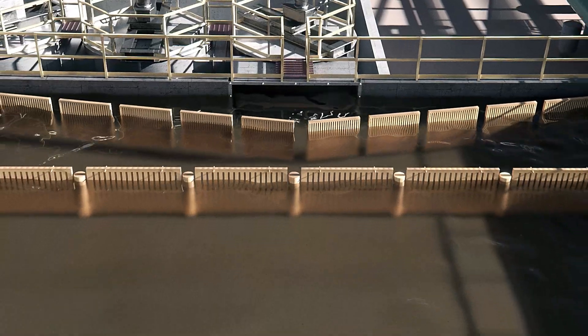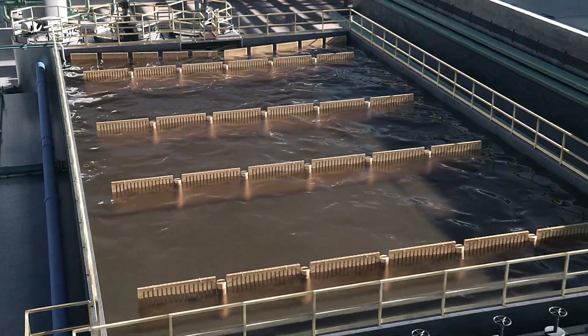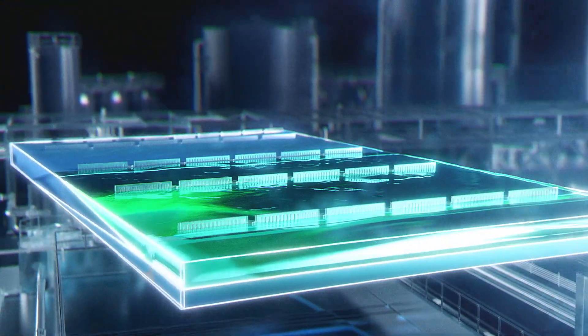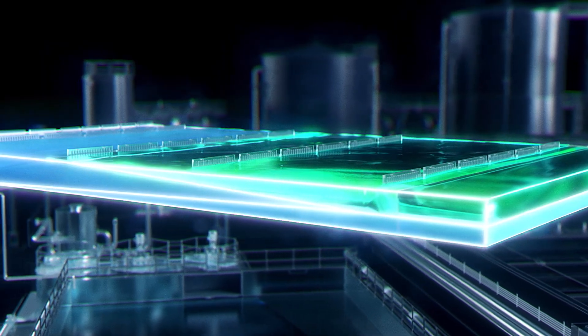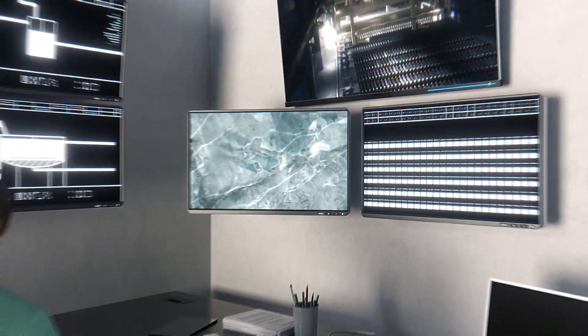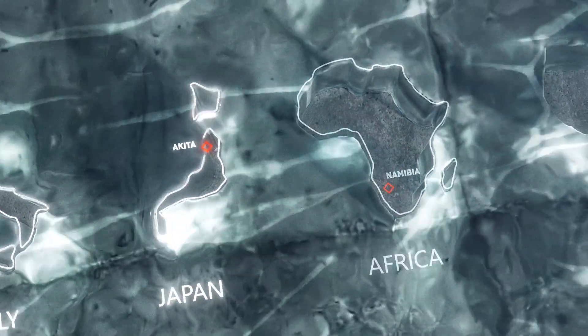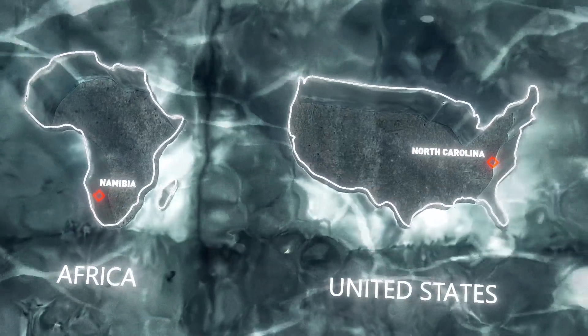Here, the solution is combined with organic liquid, stirred, and left to settle again. The zinc attaches itself to organic material and then rises to the top, like oil separates in salad dressing. This separation process is repeated until it's as pure as it can be, and it's monitored from the control room to make sure everything happens as planned. There are only four facilities in the world that use this technology, and incredibly, Befesa Zinc is the only one that produces zinc solely from recycled materials.